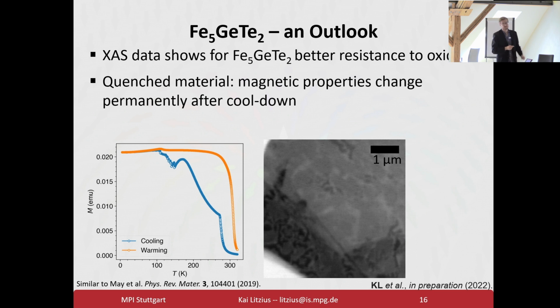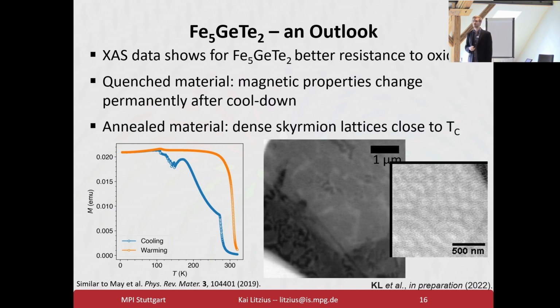Which means there have been a couple of studies on this material, and it must be very carefully checked if the material that these studies looked at is actually presenting these veins or is homogeneous. And interestingly, the annealed one is perfectly homogeneous and shows skyrmionic states even at high temperatures. And also, depending on the exact parameters or the growth thickness, etc., it shows also in-plane contrast, which could be used for spin wave applications in van der Waals systems, which is actually really interesting because spin waves, especially in the vertical direction, in the thickness, should change once you approach the monolayer limit. So this is, in particular, a very interesting system for high temperature applications.